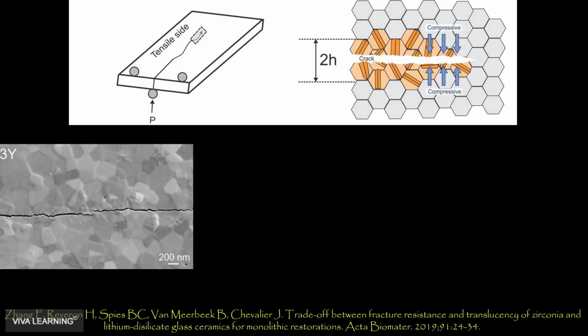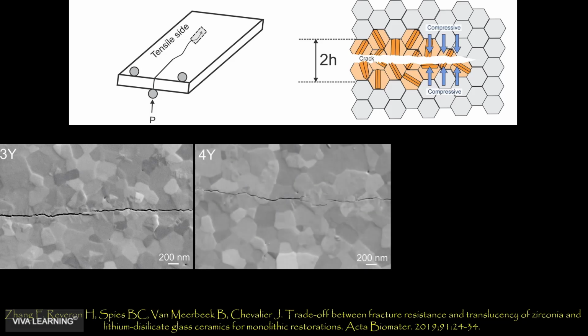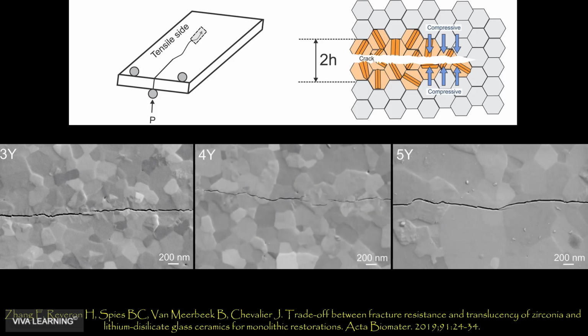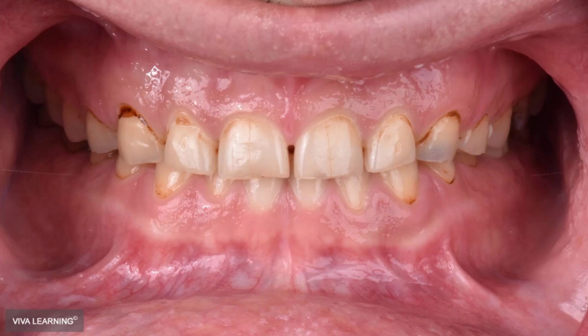Chevalier's group has shown that 3Y zirconia has the highest capability for this transformation toughening, and as we go to 5Y, we can see the line is getting clearer and not as ragged, meaning that less transformation toughening has happened. Now, if we want to go back to our case that had a worn down dentition,